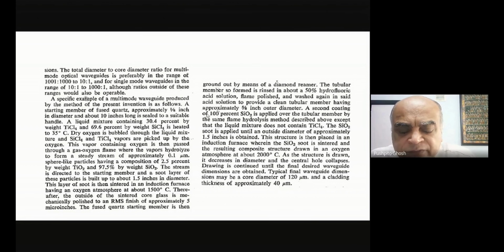So let us look at how exactly they did the other one with a relatively thick core, okay, and relatively thin cladding. Then it says the total diameter to core diameter ratio for multi-mode optical waveguides is preferably in the range of 1001:1000 to 10:1. So, I mean, this is of course the typical patent language, and they will confuse you so that you don't exactly know what they've done in many of these cases. Okay, just bear that in mind also. And for a single mode waveguide in the range of 10:1 to 1000:1.